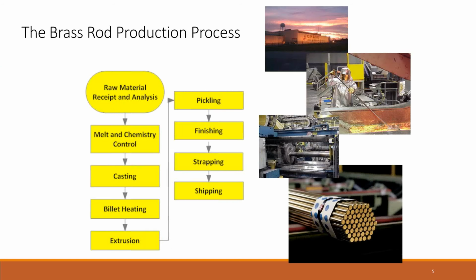Regardless of who makes it, the general process for making brass rod goes through this process flow diagram. You've got raw material receipt and testing, where you separate the wheat from the chaff, almost literally sometimes. It's got to be the right chemistry, the residual elements that we talked about before: iron, tin, nickel, manganese, aluminum, beryllium, tellurium, cadmium, arsenic, antimony. There are limits as to how much of those you can accept based on the product that you're going to cast. And there's also issues with physical shape.